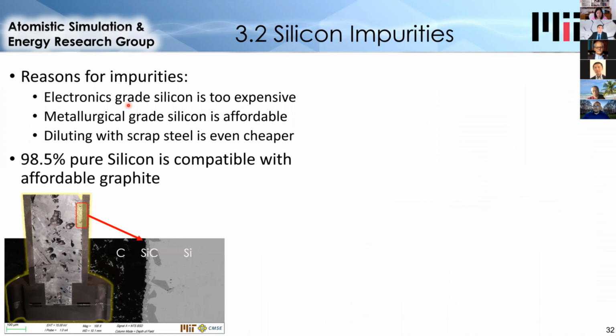Now, the next question to answer is, what is the effect of impurities in the silicon, which determines the cost of the silicon? So the challenge here is that high purity silicon, like 99.99% pure silicon, electronics grade, is far too expensive, again, around $1,000 per kilogram. So we needed to use a much less pure grade, which is usually referred to as metallurgical grade silicon. This silicon is around $2 per kilogram, and so it's affordable. And that's what we used in these experiments.